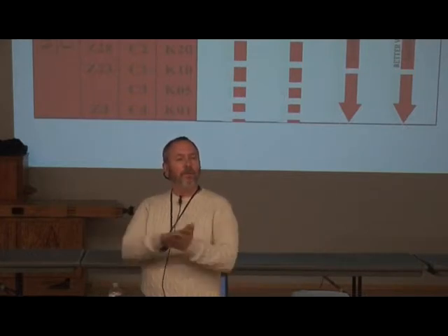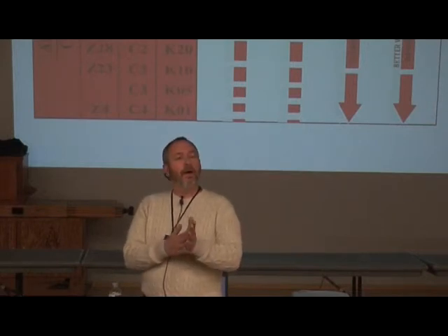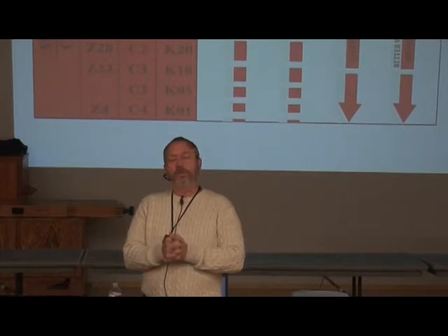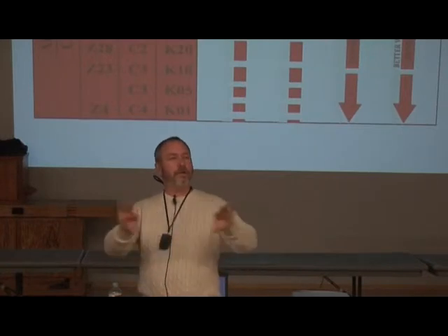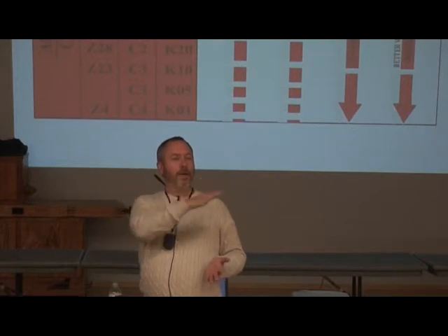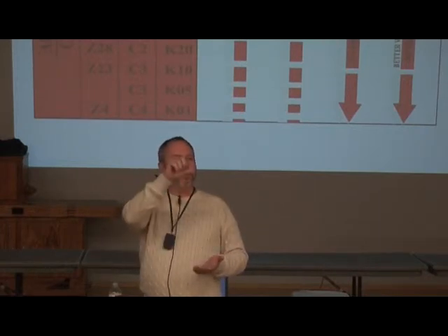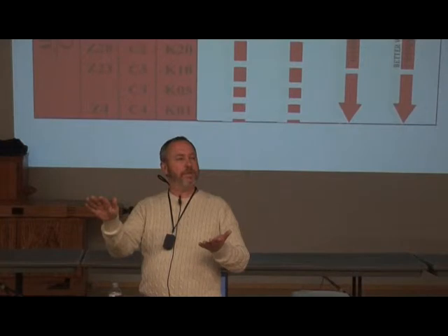What about the thought process back in ancient times where they made a sword and they kept folding it? Oh, the Damascus type, or the layering, yeah. Millions of layers or whatever. Yeah, those are real interesting how they do that. What they were doing is laying them out, folding it, and you did decarburization on the surface. So you'd fold it together. You'd have high carbon, low carbon, high carbon, low carbon, and you get this sandwich. The high carbon layers were in there for the hardness and wear resistance. The low carbon in between was for toughness.